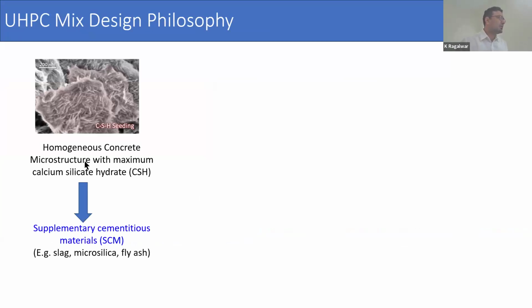So I talked about a homogeneous microstructure. The strength in the concrete paste is provided by calcium silicate hydrate. And that's where, to maximize the proportion of calcium silicate hydrate, we add supplementary cementitious materials such as microsilica or silica fume, which I talked about. There are other materials such as ground slag or fly ash, which also combine, but they have other properties as well, which can be detrimental or not as advantageous, I should say, as silica fume.